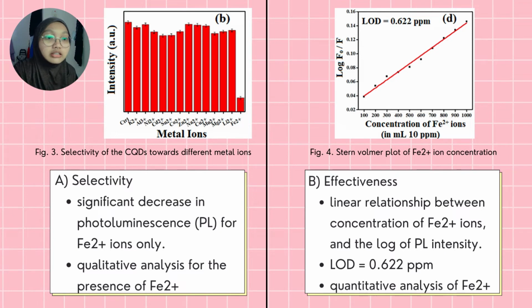This was confirmed by the linear relationship between the concentration of Fe2 plus ions and the log of the PL intensity. Also, the limit of detection or LOD for the synthesized CQDs was found to be 0.622 ppm, which is much more sensitive than carbon dots made from dopamine and plants.